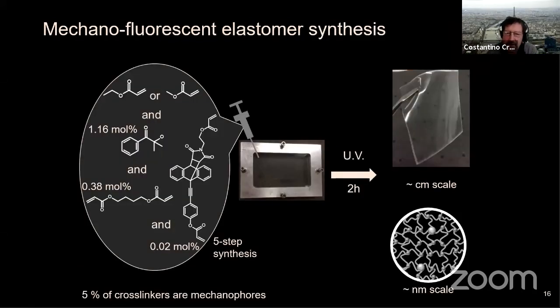So the synthesis is the same. To give you an idea, you incorporate, again, the ingredient. You put a very small amount, in this case, 0.02 mole percent relative to monomer. Then a UV polymerization of 2 hours gives you a piece of polymer like this. And this is something that you can directly test. So it's completely transparent and it doesn't emit any fluorescence when these crosslinkers are incorporated.